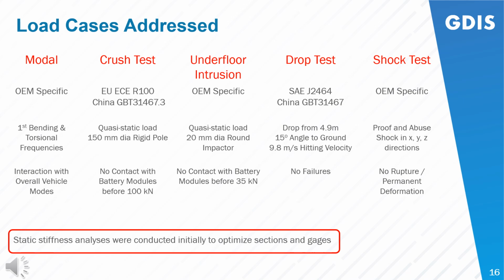Then there is underfloor intrusion, which is a quasi-static load applied through a 20 millimeter diameter round impactor to the lower panel, which is the protective shield. And the criteria is not to contact the battery modules prior to reaching 35 kilonewtons. And then there is a drop test, which is dropping it from 4.9 meters at a 15-degree angle to ground with a 9.8 meter per second hitting velocity. The criteria is no failures.